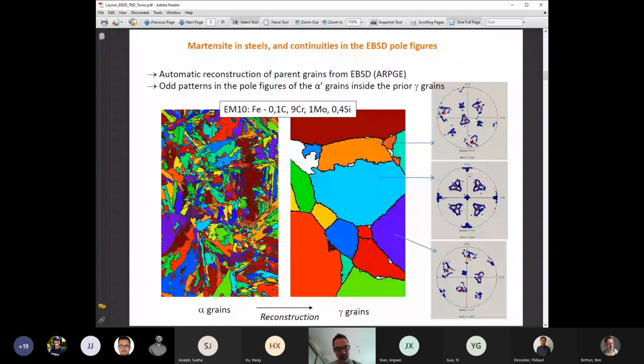On the left picture, you see the martensitic microstructure, fully martensitic. It's an EBSD map. On the right side, you see the prior austenitic grains after reconstruction. It's the austenite that existed at high temperature, and then disappeared, transformed into martensite at low temperature. What was also of interest to me is that if you look inside the prior austenitic grains at the orientation of the martensite, we know there are 24 variants of martensite. So we could expect to get 24 discrete features in the pole figures.